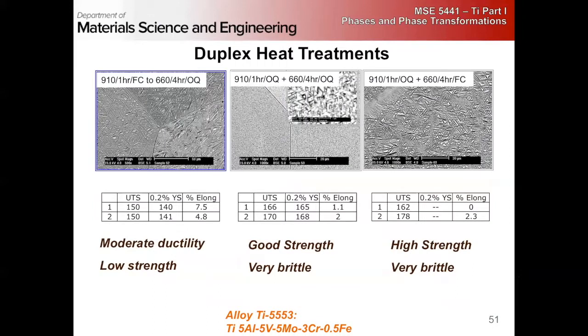So often you can get a much wider range of structures by these duplex heat treats. Essentially if you look at this, you furnace cool and then an age plus oil quench, giving a nice basket weave type structure, versus oil quench and then the same type of aging, where we have a very fine alpha distribution. And then here we do an oil quench and then a furnace cool. And we notice in these two conditions, both of these are very brittle.